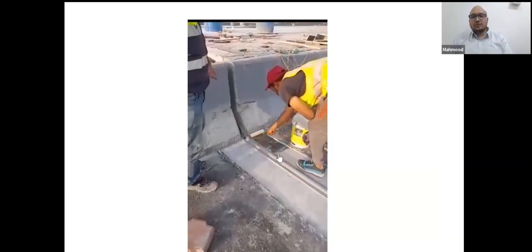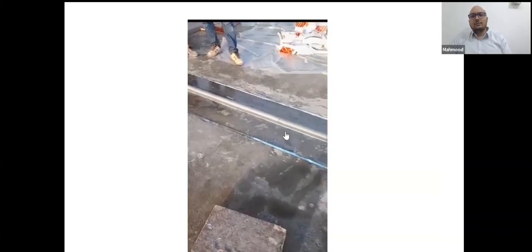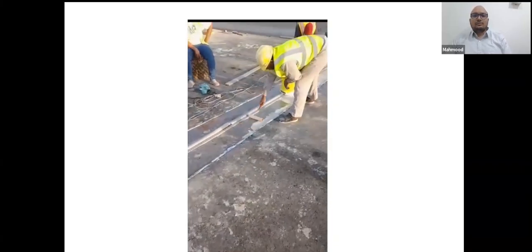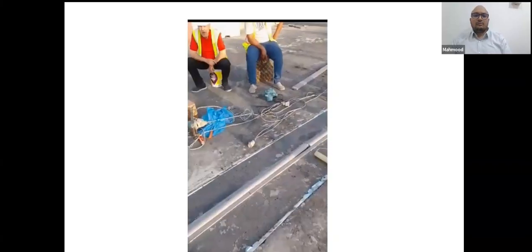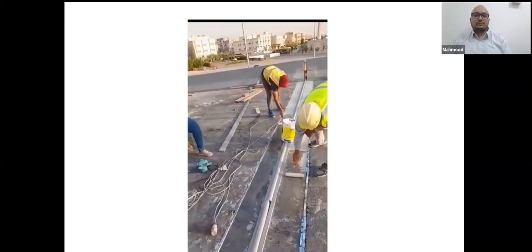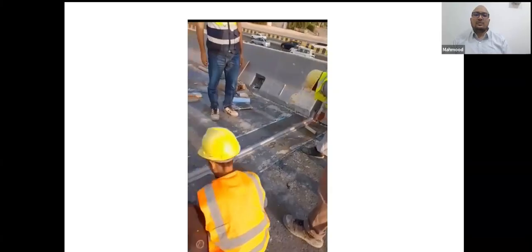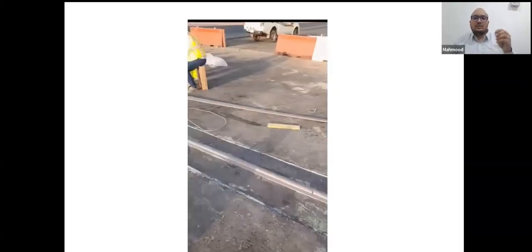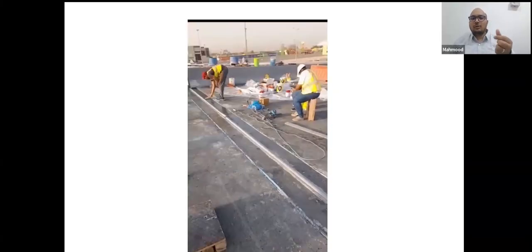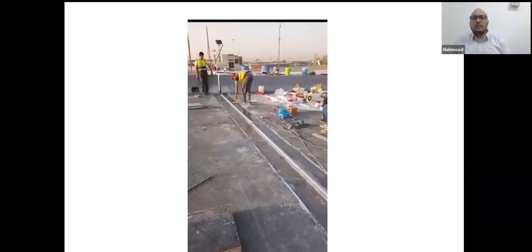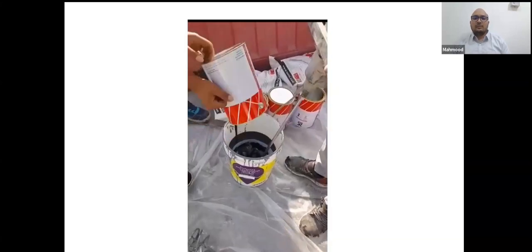Surface preparation is a must. You need to remove the dust. You apply an epoxy-based primer, base and hardener mixed for 3 minutes, and then they're applying it. After it's become touch dry, touch dry means when you touch it, it should not come on your hand. Then you will mix the main material, which is epoxy base, hardener, and filler, which is also resistant to fire.